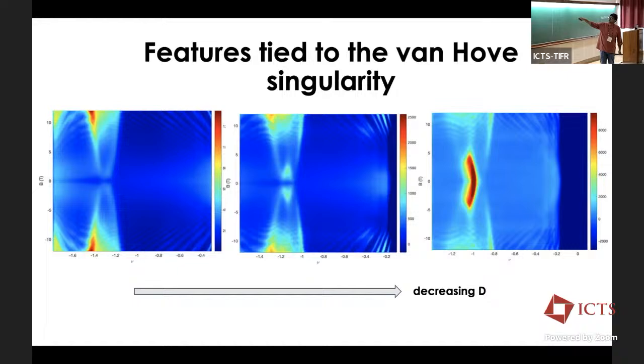This is done for a different value of electric field. And finally, if I tune the electric field just right till I reach that insulating phase, at this particular value of the electric field, I've hit that insulating phase. You can see that insulating phase, which appears precisely at half filling. But at these values of electric field, there is no insulating phase at half filling. And I want to talk to you about what the magnetotransport looks like at these values of electric field. Okay, so I'm going to concentrate primarily on the Hall effect.